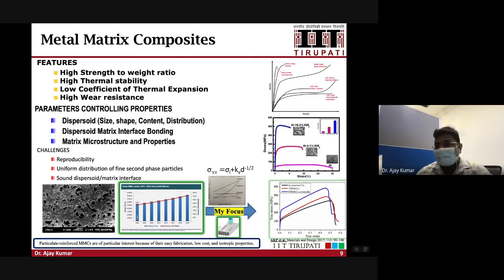So that's why these composite materials have limited use in the automotive or aerospace industries. And there is a challenge. The challenge is reproducibility, uniform distribution of the fine second phase particles, and a sound dispersoid matrix interface. So here we are focusing on developing composite materials where we can get high strength as well as high toughness without any reduction in the percentage of strain. That is why we are using an innovative idea of utilizing the friction stir processing method to make the new composite materials.